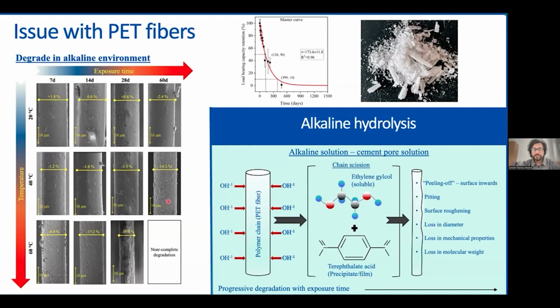And you can notice, for example, how the diameter of the fiber is reducing. Also the surface damage, the pittings, are easily visible in these images due to prolonged and accelerated aging in alkaline solution. In the most severe condition, for example 60 days at 60 degrees, what we saw was nearly complete disintegration of the fiber. And here is the image of what the fibers actually look like after this exposure. They were completely disintegrated.